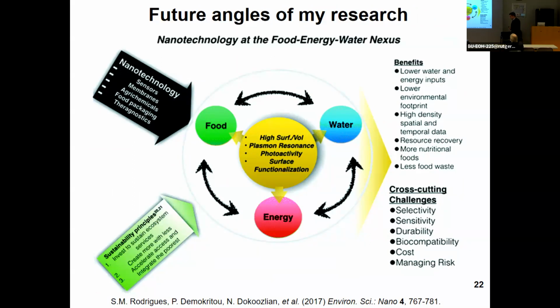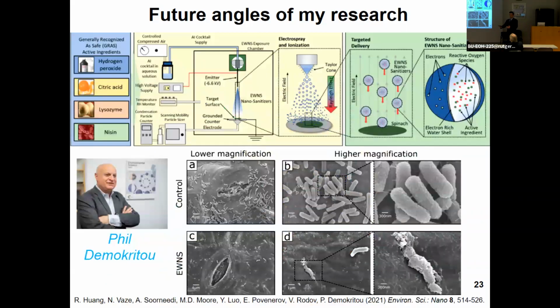And nanotechnology can actually provide solutions to such emerging societal problems, like, for example, using sensors similar to those that I showed you earlier. In this regard, your institute has members that have already worked on this field, such as Professor Demokritou, who developed, for example, in this case, water-based aerosols that contained natural pesticides like hydrogen peroxide and citric acid. Again, in this case study, these water droplets, essentially, that contain these compounds, were sprayed on top of spinach leaves to clean their surface from E.